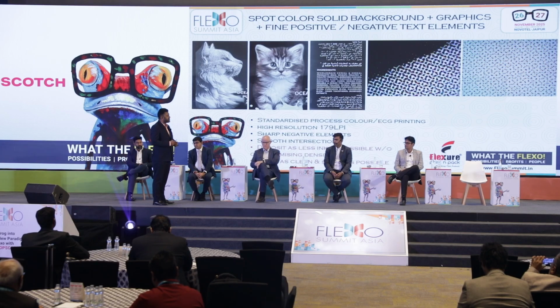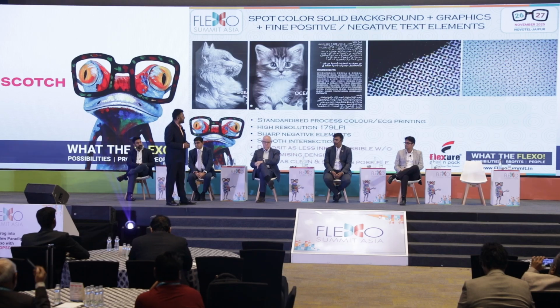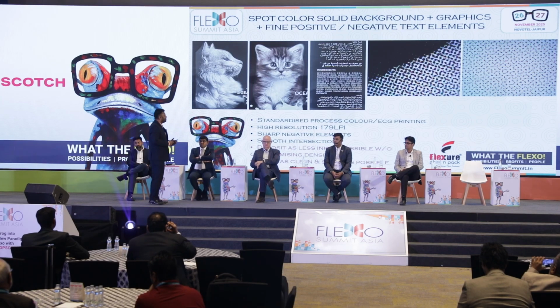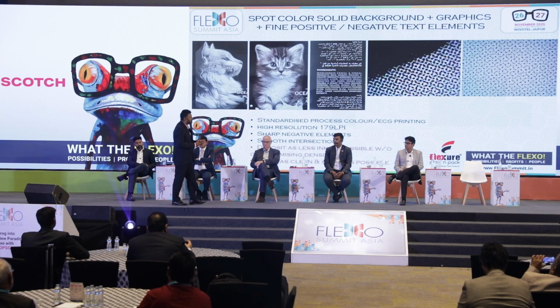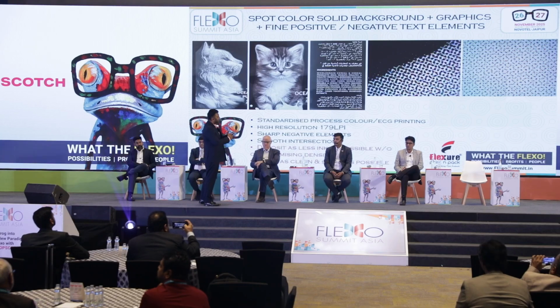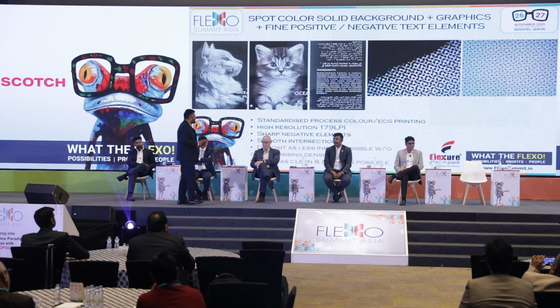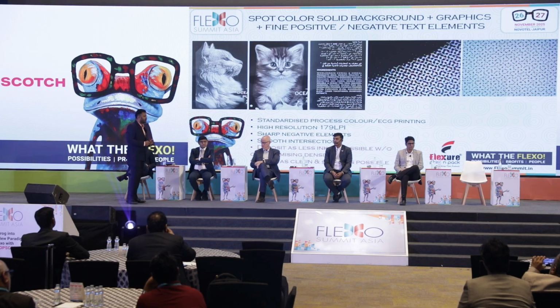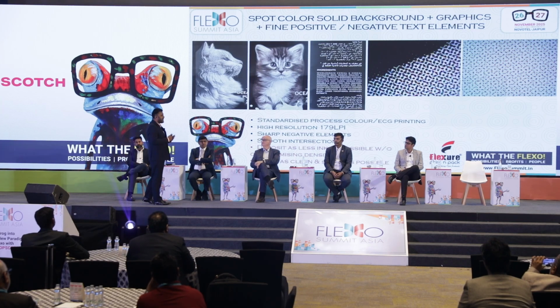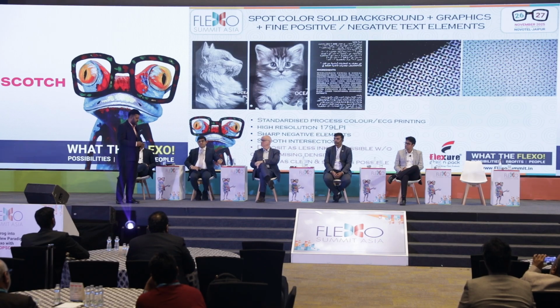This has been done in reverse of 4 colors. With the advanced automation in the CI presses, we can achieve 4 color negative elements also. As you can see, there is also smooth intersection between the solids and the halftones, and very fine small dots, somewhere around 35 to 40 microns, have been printed very smoothly. So what we say is, in Flexo, deposit as little ink as possible without compromising density, and print as clean and as sharp as possible if it is graphics or text elements.